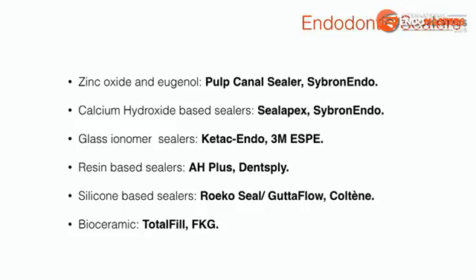We will continue mentioning calcium hydroxide sealers. They were developed for therapeutic activity. It was thought that these sealers would exhibit antimicrobial activity and have osteogenic and cementogenic potential. Unfortunately, these actions have not been demonstrated. And since solubility is required for the release of calcium hydroxide and sustained activity, the benefit of having an active medicament present was defeated by the need of having some type of impermeable seal.